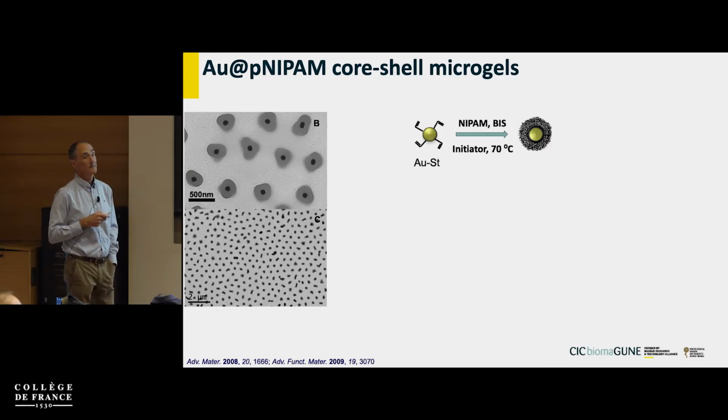And you will tell me, or I would say, they don't look very nice because the shells don't look very spherical, right? Well, this is, of course, a sign of the flexible nature of these shells, because when you are looking at them in the electron microscope, they basically collapse because there is no water inside. So what you see is actually something like a fried egg.